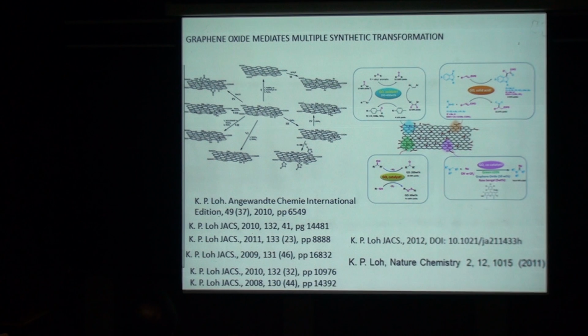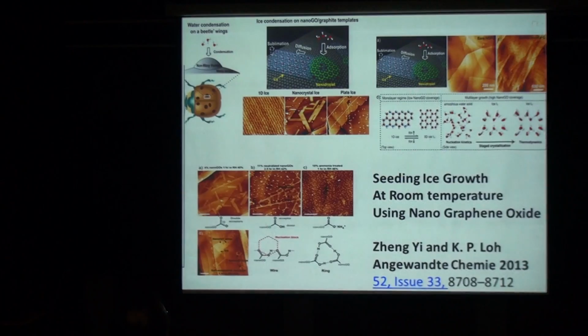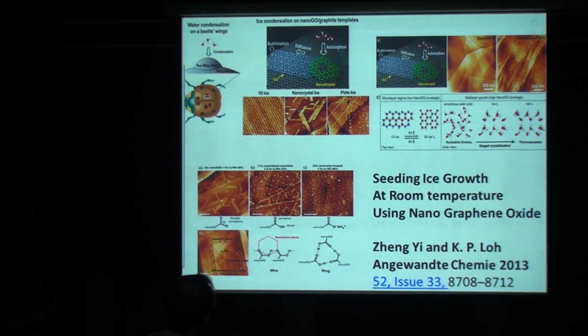So this is interesting because it means that the material can undergo ionic interaction. And with all these oxygen functional groups, it becomes a handle for performing different types of chemistry. It can be an oxidant, because some of the oxygen groups can be supplied to a chemical reaction. It becomes an acid because it can undergo protonation and deprotonation. It can react with a base like amine and so on. The graphene oxide is very hydrophilic because of these oxygen groups. These oxygen groups are ionic, hydrophilic, meaning they love water. So recently we did an interesting work.